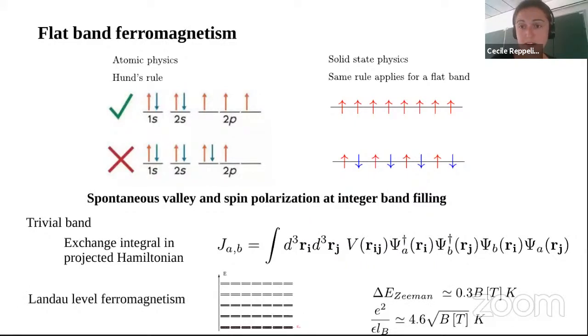But away from that context of the trivial band, you can also think of the case of Landau level ferromagnetism. This is what I was mentioning in the very beginning of the lecture. When you have Landau levels, you have a spin degree of freedom. If you consider the case with filling fraction 1, you completely fill the lowest Landau level, but just corresponding to just one spin. Since you have a Zeeman effect, you could naively think that the fact that you have an insulator in this case, the gap comes from this Zeeman effect, but it's really not the case because the Zeeman effect is very small in energy.